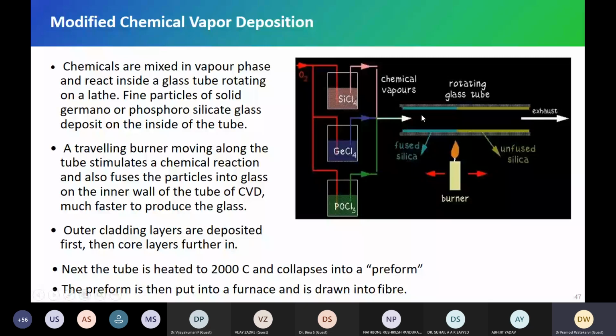Remaining SiCl4 and SiO2 go out to the exhaust. We have a water bath there, through which the SiCl4 and others are collected and removed. So it is a very simple method, modified chemical vapor deposition. We can make it in your laboratory also. Just take a glass tube. You only have to ensure that there is no leakage. That is the main thing. And we can pass SiCl4 particles.